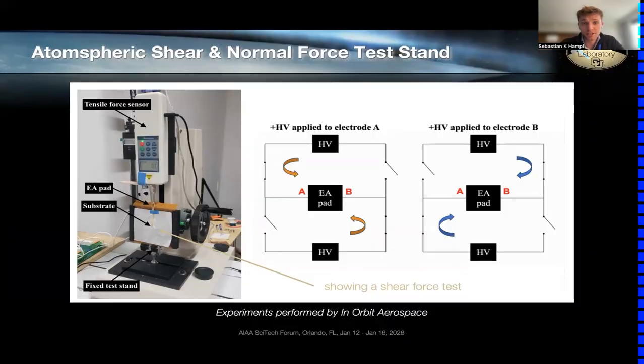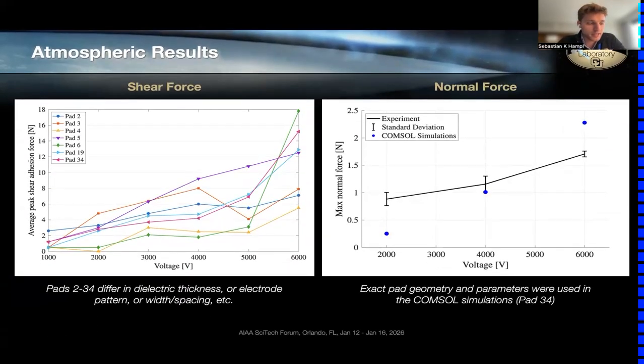So this is the atmospheric shear force and normal force test stand. In this case, on the photo configured to test shear forces, one can see the force sensor, the electroadhesion pad, and the paper substrate in this case that's being pulled on. For the atmospheric results, we tested both shear and normal forces, as I said before, and one can see that shear forces, and that is consistent with previous studies, are much stronger than the normal forces. In-Orbit tested multiple different pad configurations, and as you can see, they all perform differently, but they all show the same trend that going to higher voltages increases the electroadhesive force that you're measuring significantly. Whether the rate is exponential or linear differs between the pads, but it is important to note that the shear forces we have seen are much higher than in previous studies. But this also is due to us applying higher voltages than those previous studies.